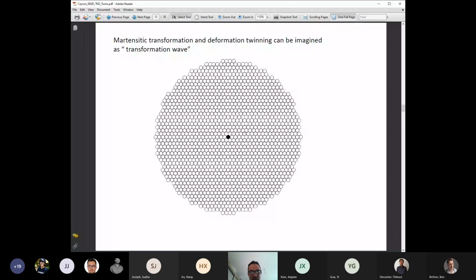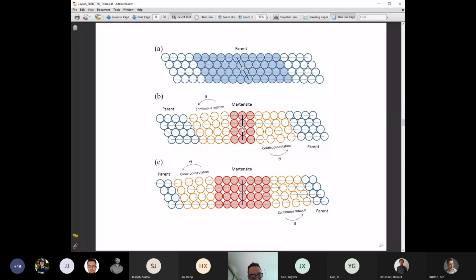Here is another type of representation to show you that this continuous rotation is necessary to accommodate the martensite with the surrounding parent austenite. And that's exactly what I noticed. My first question was about these continuous features in the martensite, and to me, the explanation is here. So that was quite satisfying, to know that you can take an atomistic model to explain something that is more mesoscopic, that is the continuous rotation field observed by EBSD.